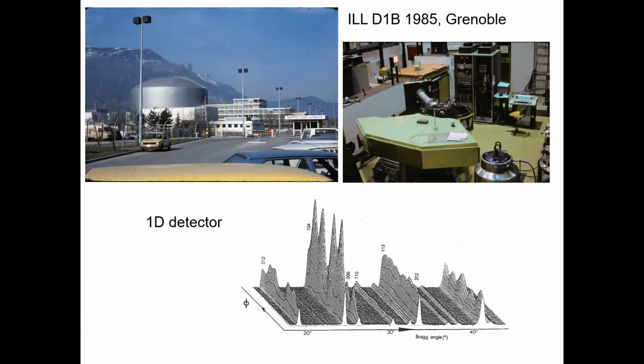For me, it started in 1985 at ILL in Grenoble, where they had this interesting detector which had a continuous 1D spectrum. So you could measure a spectrum at once, and then you could rotate your sample and you get different intensities indicating that in different directions of a sample you had differently oriented crystals.